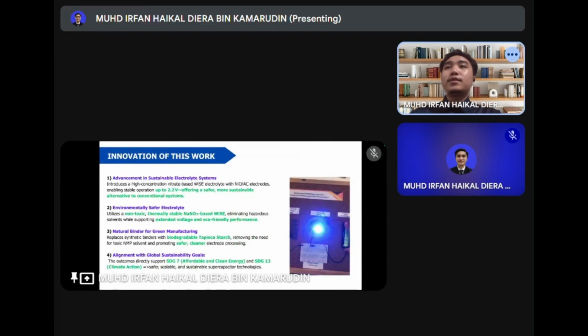Lastly, innovation of this work. Our project improves supercapacitors in a greener, safer way. The key innovations are, first, a safer electrolyte system. We use a high-concentration nitrate-based aqueous electrolyte that works up to 2.2 volts. It is more stable and less dangerous than traditional electrolytes. Second, eco-friendly materials, where we use non-toxic sodium nitrate and avoid harmful solvents. It is also safer for people and the environment.